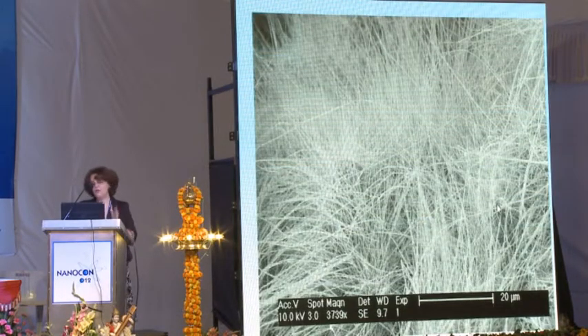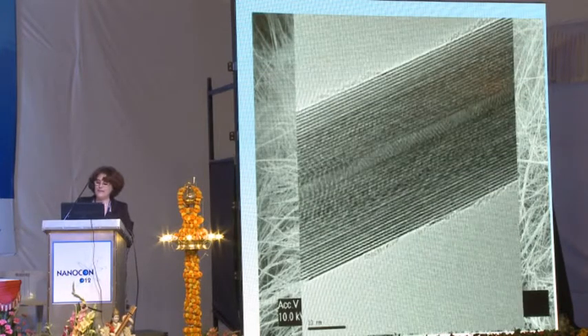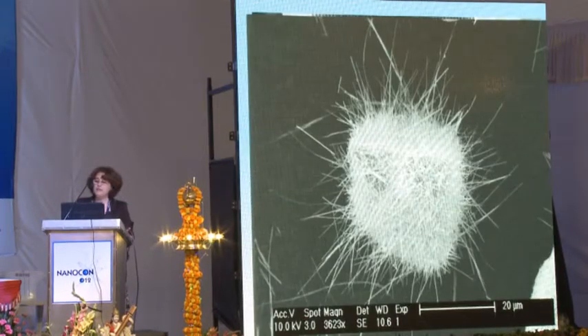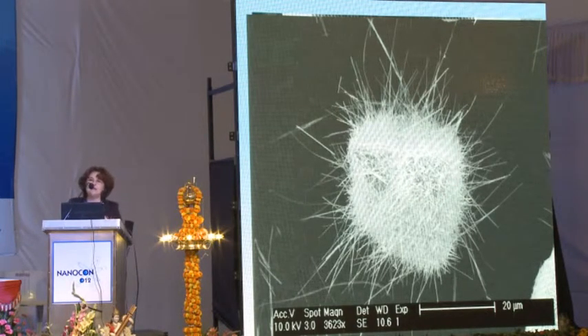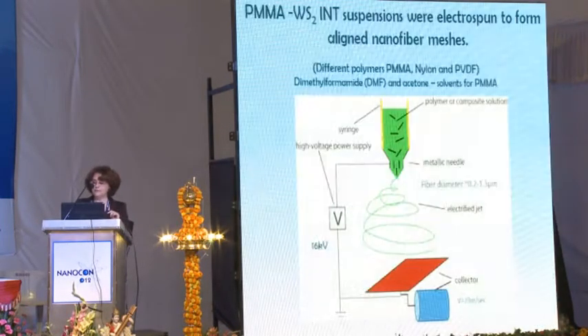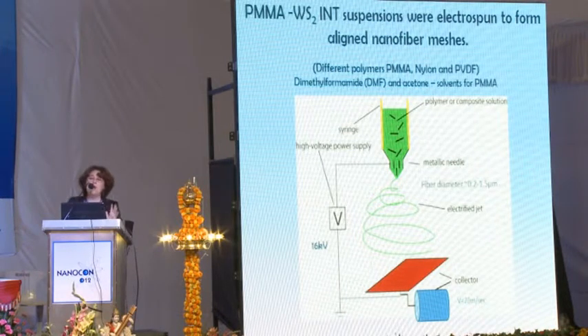I want to show you first of all these beautiful pictures of nanotubes we obtained. The first is SEM. This is the TEM picture. These particles range in size from a few microns to 50 microns, averaging 10 to 20 microns, and in diameter they average 100 nanometers. They're bigger than carbon nanotubes. They have other properties.